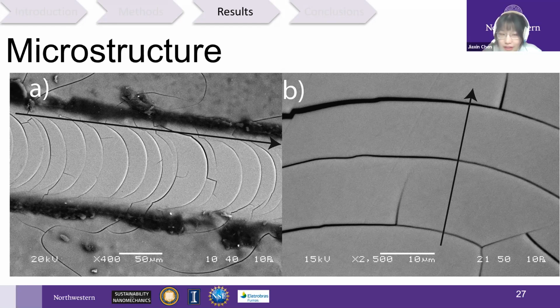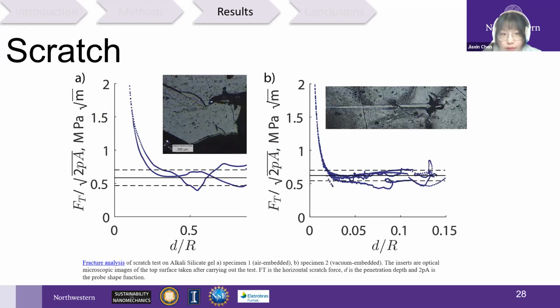Yeah, that's definitely a great question. But for my understanding, maybe not correct as well, when we calculate our fracture toughness, we didn't think about the energy dissipated from the small cracks. We only consider the big cracks, like the curved crack surface, as shown here. So when D over R is really large, FT over square root of 2PA goes horizontal and converges to a value, and we obtain that value as our fracture toughness.